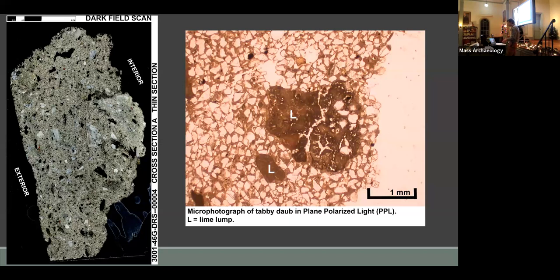But Tabby may have been produced using what's called a hot mix method, where sand was mixed directly into quicklime and the resulting steam was enough to adequately slake the lime. And so the presence of lime lumps featured here on the right, the big round mass. Basically, the presence of these particles in the Tabby daub thin section suggests the use of hot mix instead of lime putty, which implies the mix was applied to the frame really quickly after burning the shell into quicklime. So this is something that is very ad hoc. It was not kept for long periods of time, or not stored.